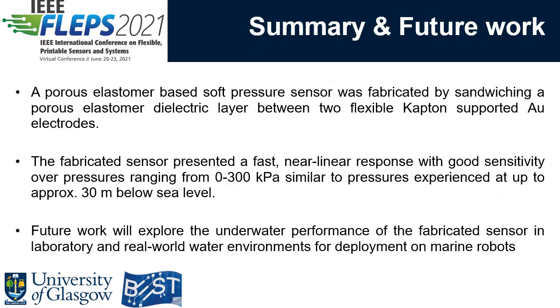In conclusion, a soft capacitive pressure sensor was fabricated by sandwiching a porous elastomeric dielectric layer between two electrodes on flexible Kapton substrates. The fabricated sensor was tested over a wide pressure sensing range under pressures similar to those experienced at up to approximately 30 meters below sea level. In this range, the sensor presented a 94.5% near linear response and sensitivity of 0.7 per pascal. The sensor also featured fast response and recovery times as well as good stability, thus proving its applicability for a wide range of pressure sensing applications, particularly underwater robotics for real-time monitoring and surveillance operations.